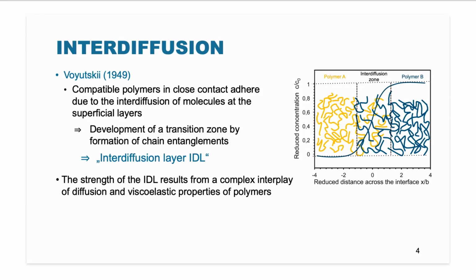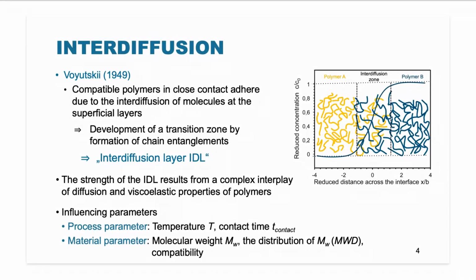The strength of the interdiffusion layer results from a complex interplay of diffusion and viscoelastic properties of the polymers. Influencing parameters have been shown to be process parameters like temperature and contact times. On the other hand, we have material parameters such as the molecular weight, the molecular weight distribution, and the compatibility of the polymeric material.